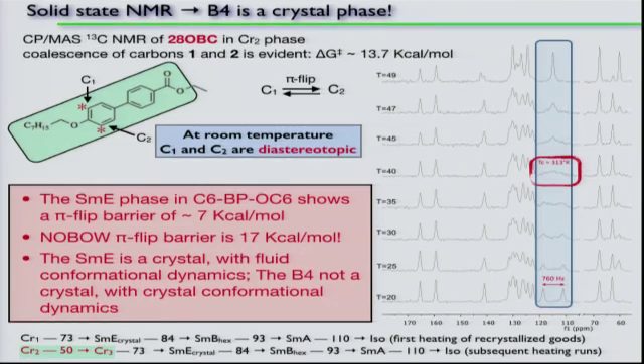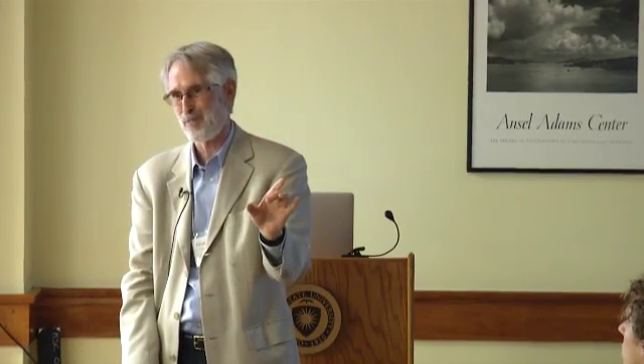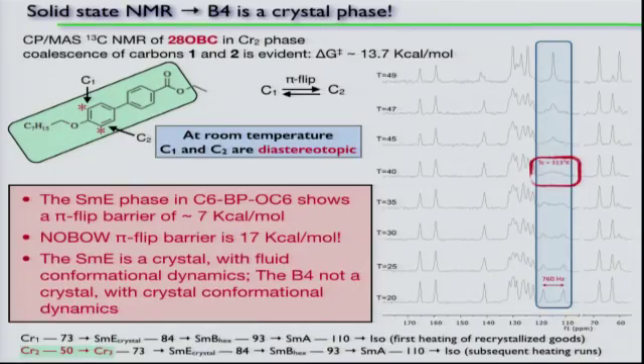So it's like parts per million difference in these frequencies of these absorptions. Parts per million. Okay? So in order to be able to see that, you have to look at it for a long time. It's the Heisenberg uncertainty principle. Okay? So if those carbons start exchanging sites, once that gets fast enough, and it doesn't have to go that fast, then those two peaks, as you heat this up, the rotation around this thing starts to happen.